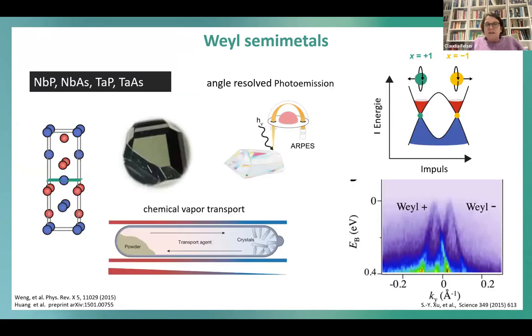So this is a Weyl semi-metal. There was this prediction, which is a nice thing of topology. So suddenly theory predictions work. Okay, some people predicted something, but they were very complex materials, difficult to make. But with niobium phosphide and niobium arsenic, the material could be made by chemical vapor transport. We could make very nice single crystals, and it has no inversion symmetry, exactly what you need. And the Weyl points are very close.